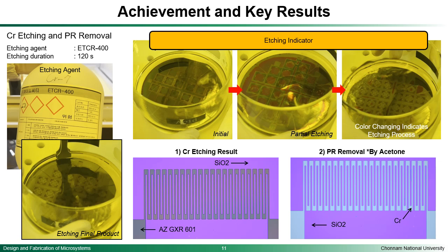So we were using the etching agent ETCR 400 to etch the chromium, and we utilized this etching for a duration of 120 seconds, and we can see here the etching final product. But for the etching indicator, we can see from the slides on the right side, from the initial and also the partial etching, that the etching is going on our wafer based on the color changing of the surface of the silicon wafer. And then after the change completely stops, it means that the wafer is at the final etching, and then we can take our wafer out.